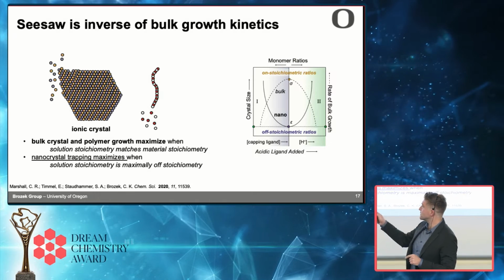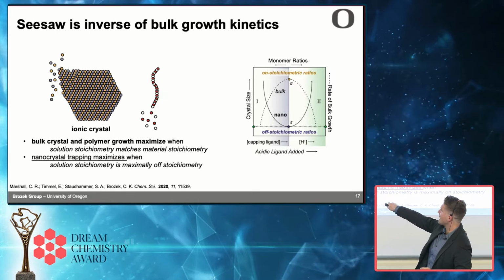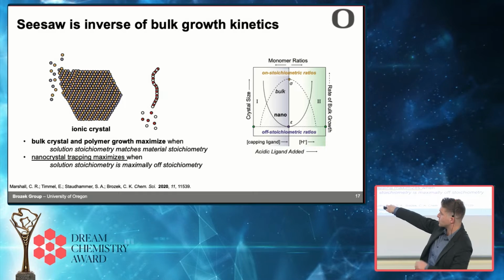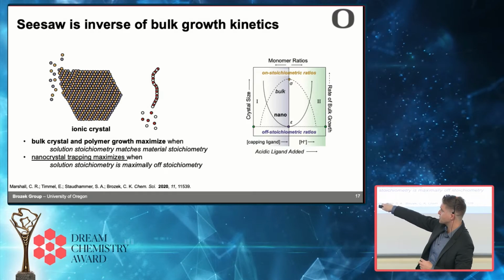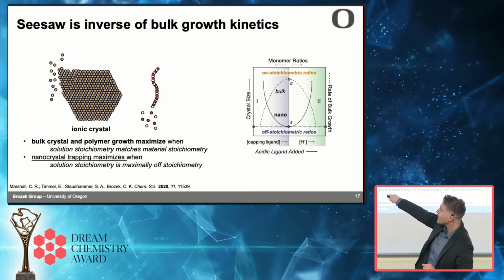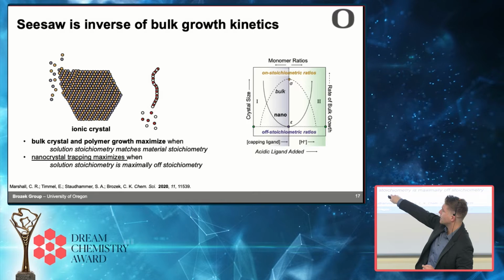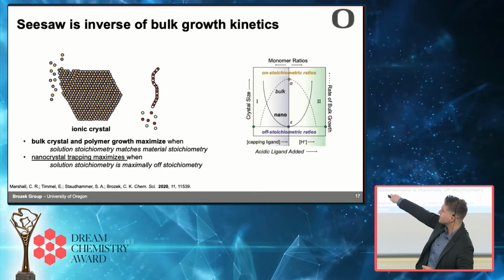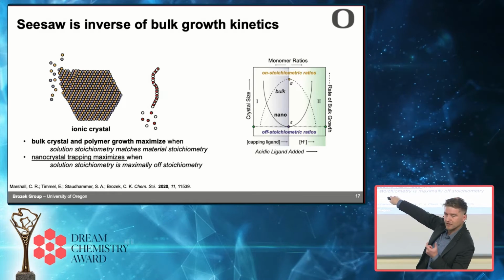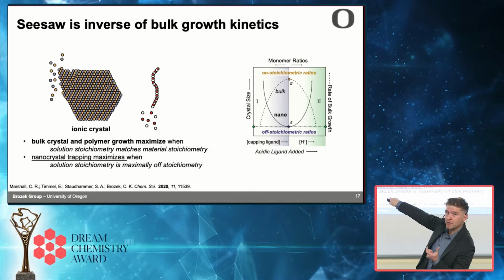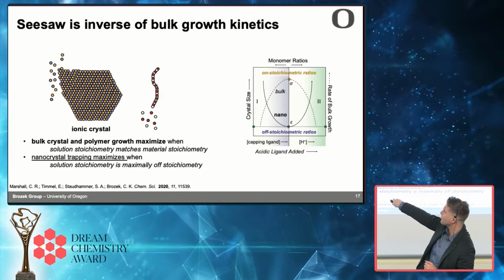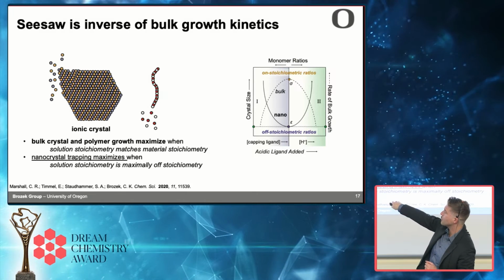So in other words, and this is a scheme that I came up with, but this very much shows up again and again in the literature for these fields, where they say the rate of growth of a polymer or an ionic crystal is maximized at a stoichiometry that looks as much as possible like the thing you're trying to make. And if you move away from that stoichiometry, the rate really falls off.